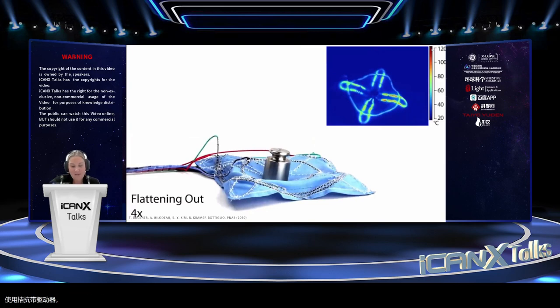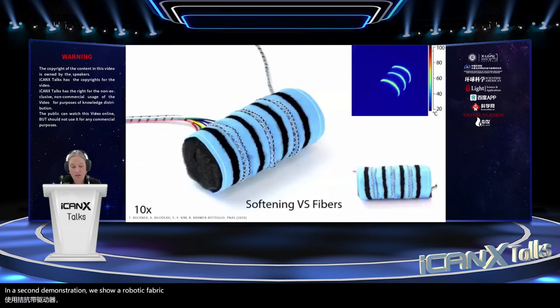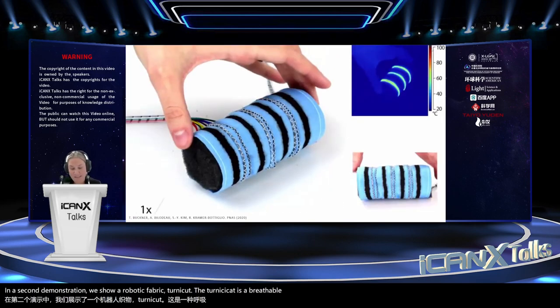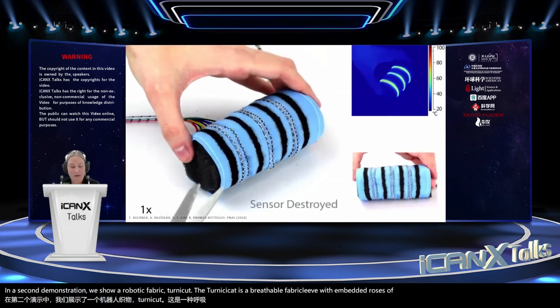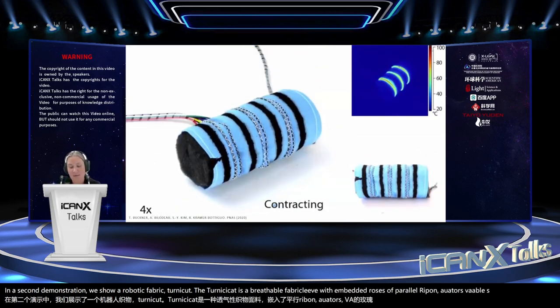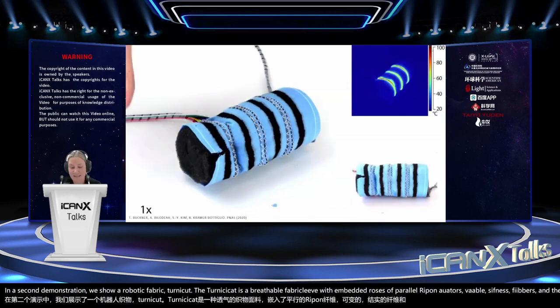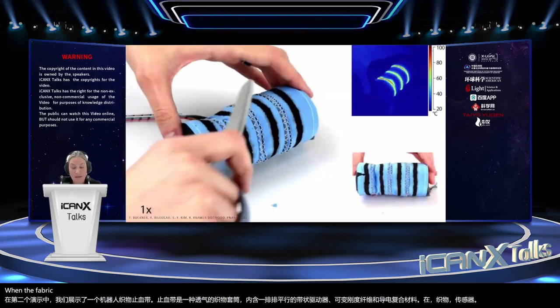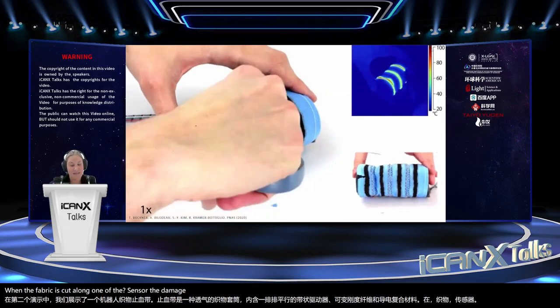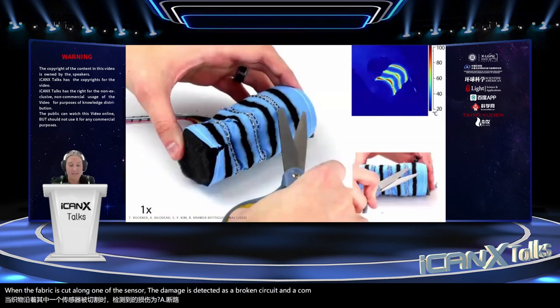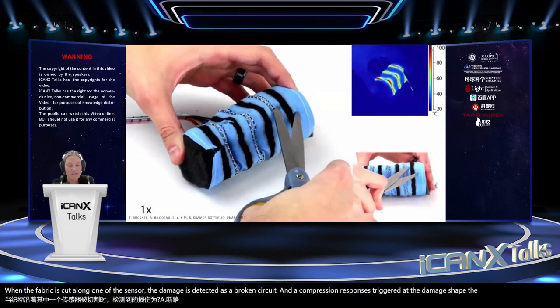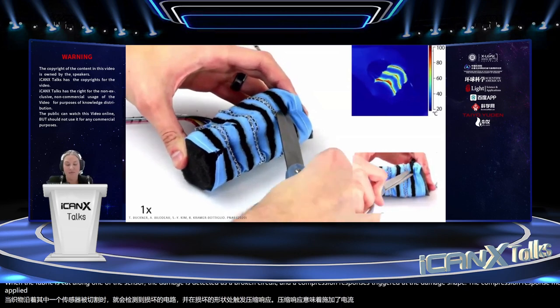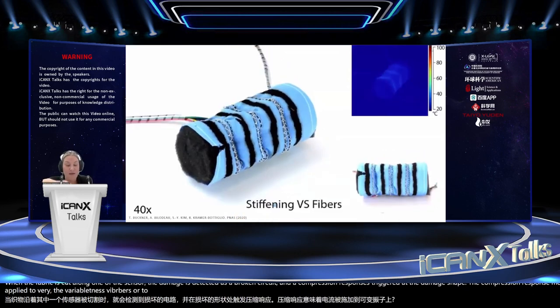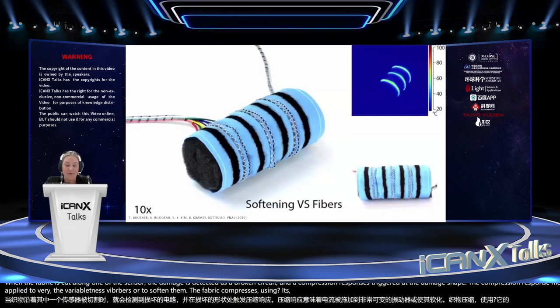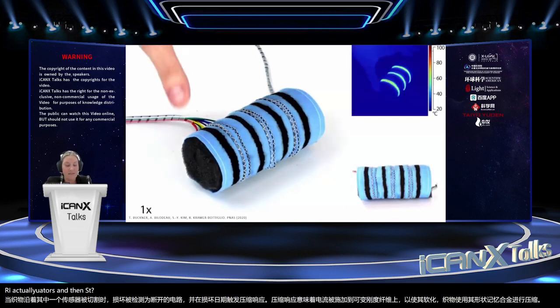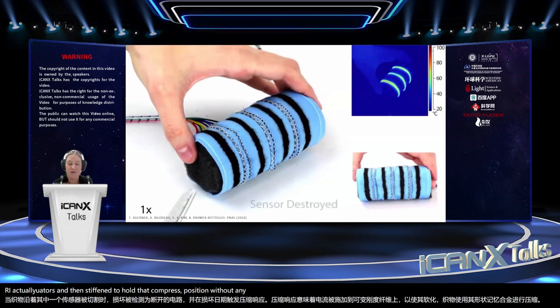In the second demonstration, we show a robotic fabric tourniquet. The tourniquet is a breathable fabric sleeve with embedded rows of parallel ribbon actuators, variable stiffness fibers, and the conductive composite in fabric sensors. When the fabric is cut along one of the sensors, the damage is detected as a broken circuit, and a compression response is triggered at the damage site. The compression response means that the current is applied to the variable stiffness fibers in order to soften them. The fabric compresses using its shape memory alloy ribbon actuators and then stiffens to hold that compressed position without any further power supply.